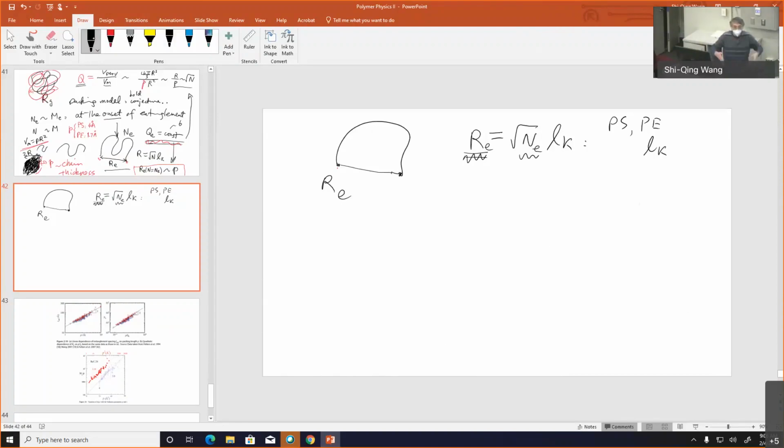Given a fixed volume, I have changed this thickness. Same volume. If I put them in, of course, I can only fit fewer chains if the chain is thicker. That's styrene. And so the only way I can fit more is to give me a bigger volume, right? And since I need to fit 6 chains in my volume to reach entanglement, styrene simply has to be longer. So this is all quite trivial.